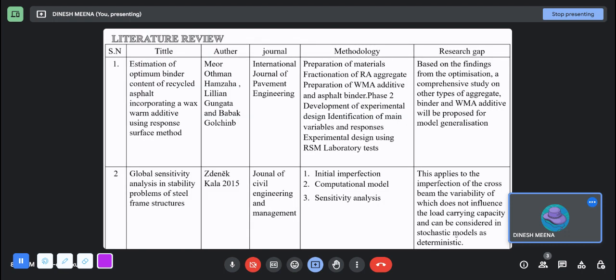Then, the literature review part, in which estimation of the optimum binder content of recycled asphalt incorporating a warm mix additive using a response surface method. In this paper, the adopted methodology was preparation of the materials, fractionation of recycled asphalt aggregate, preparation of the WMA additives and asphalt binder. Phase two was development of the experimental design, identification of main variables and responses. Experimental design using the RSM, laboratory tests, in which the research gap based on the findings from the optimization, a comprehensive study on other types of aggregate, binder and WMA additives will be proposed for model generalization.